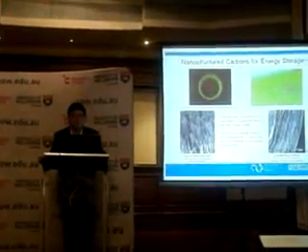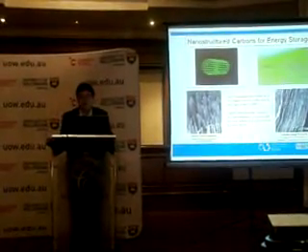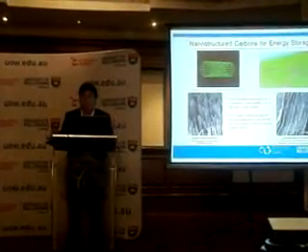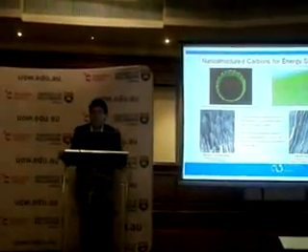And then there's this other really simple, amazing discovery that happened just a few years ago and won the Nobel Prize this year, and that is the discovery of graphene. Graphene is not sophisticated. If you take a pencil, it's made of graphite. We take that graphite, we boil it up in some sulfuric acid or some concentrated oxidizing agent, and we'll form graphitic oxide in solution. You can reduce that with very simple chemistries to graphene. That's it, simple chemistry. You can't get any simpler than that to produce at very large scale nanoparticles of carbon that have extraordinary properties.